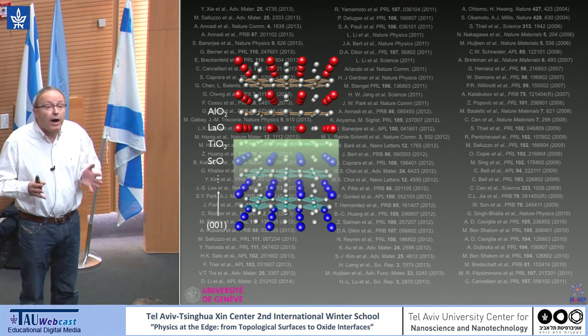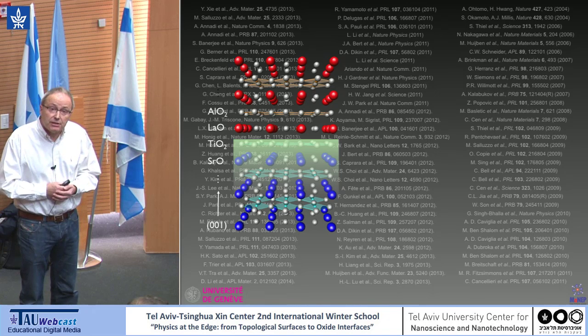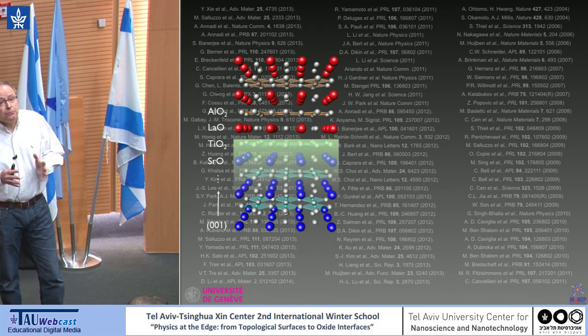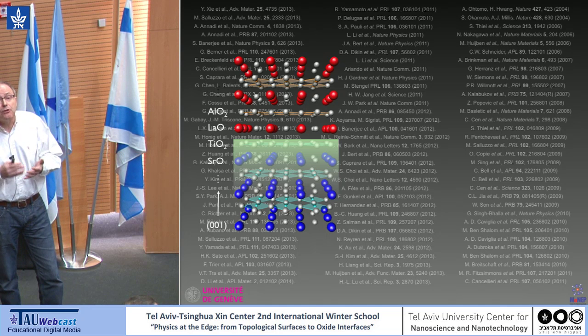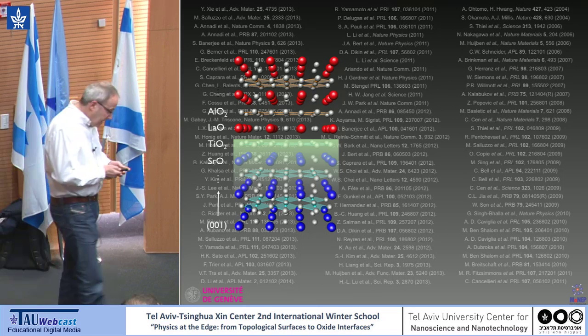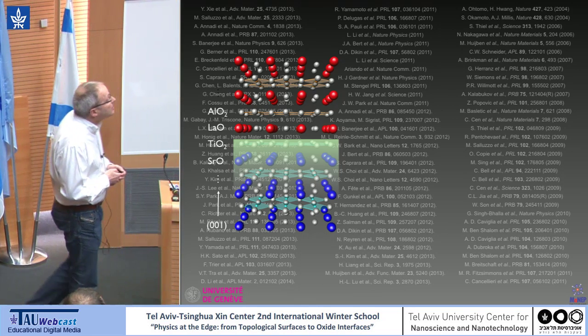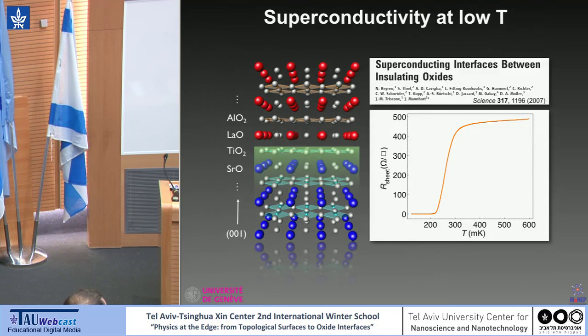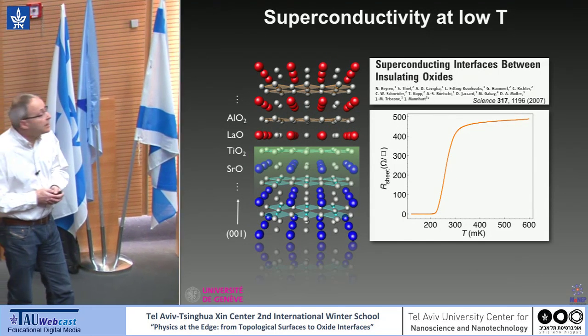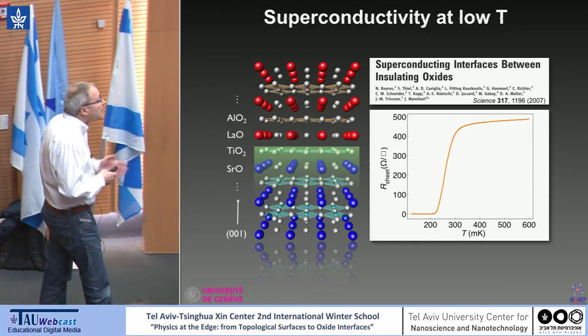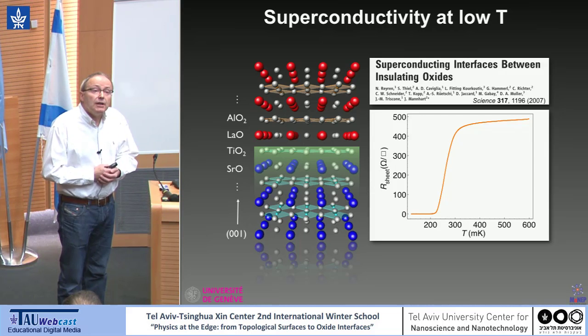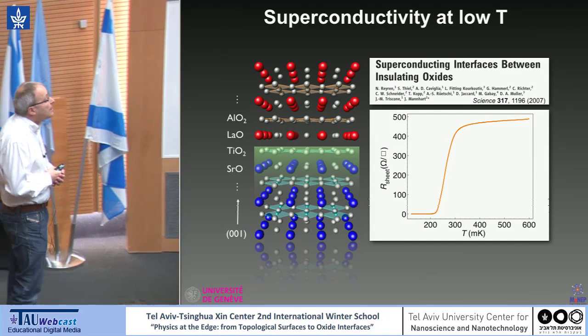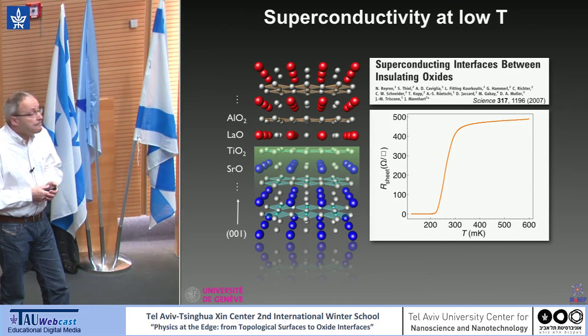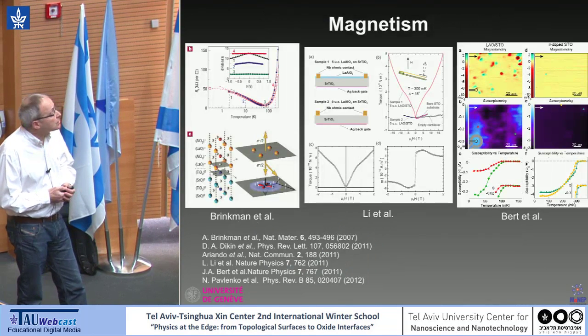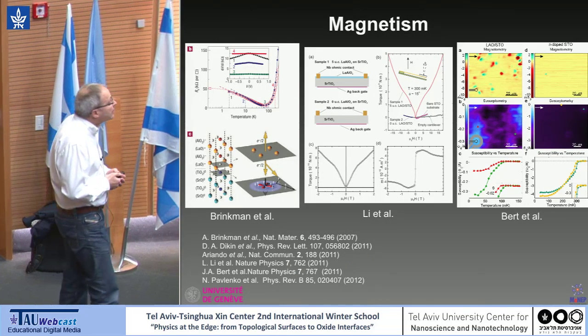And I think there are different interests for the system. One, we would like to understand why the interface between two insulators is conducting. This is one thing. And the other thing is that we have in the system mobile electrons in a complex oxide, and so we can hope for interesting properties. In 2007, in collaboration with Jochen Mannhart and his team, we discovered that this interface is also superconducting. You see here, again, the sheet resistance versus temperature, and you see the superconducting transition with a low critical temperature of about 250 millikelvin.